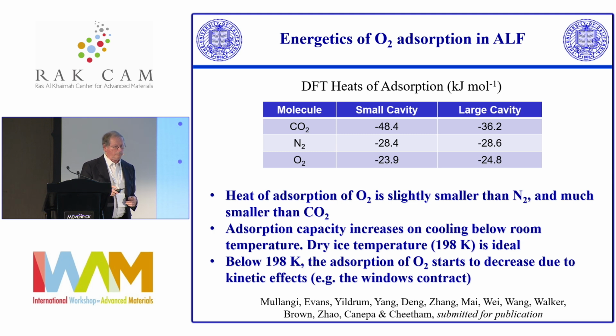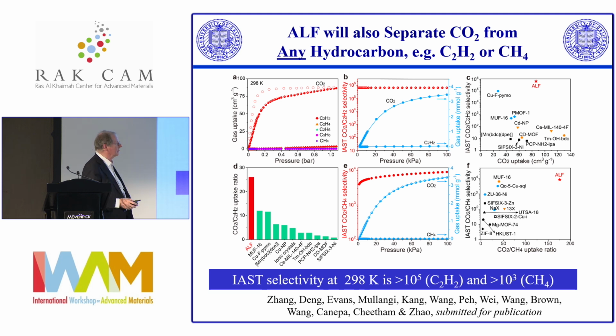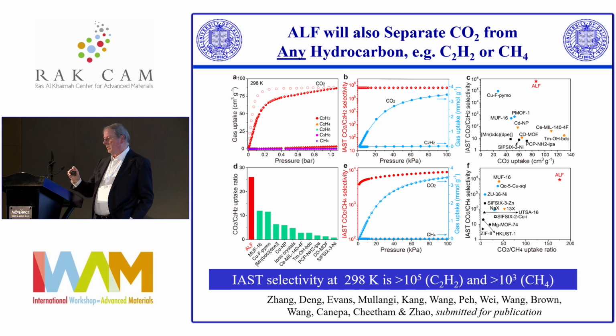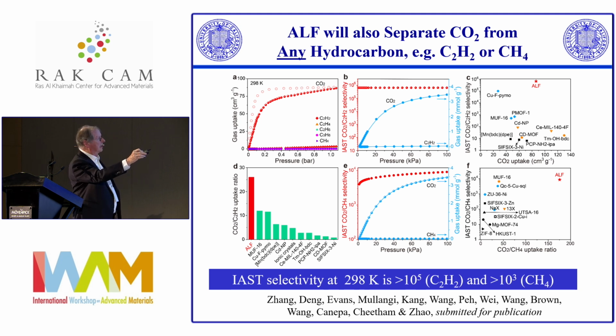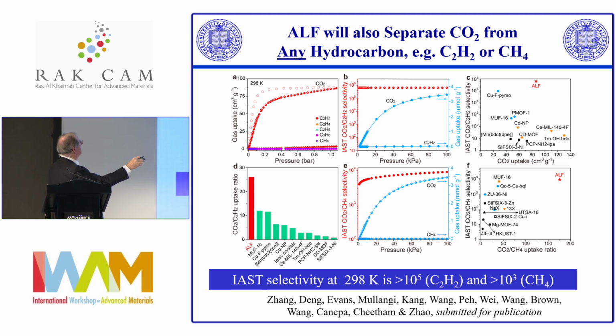So let's go back to the CO2 for a moment. This is another tranche of work, a kind of third tranche of work. ALF will separate CO2 from any hydrocarbon, including acetylene, which has a smaller kinetic diameter than CO2. So that's a bit of a puzzle, and we've done calculations. I think we now understand it quite well. But these are the adsorption isotherms for methane, ethane, acetylene, ethylene, and propane, and none of them go into ALF, and this is the CO2 under the same conditions.